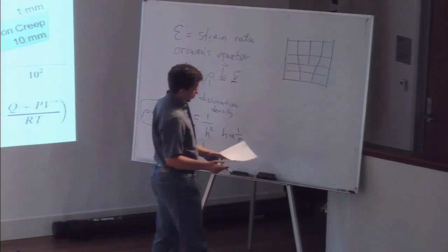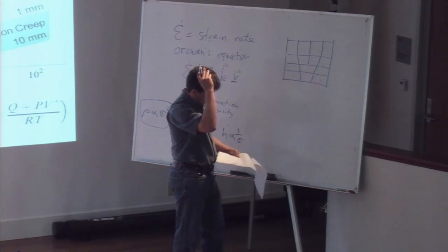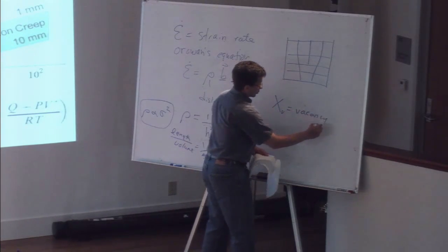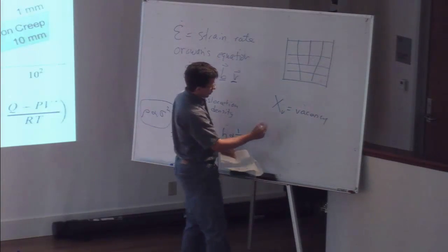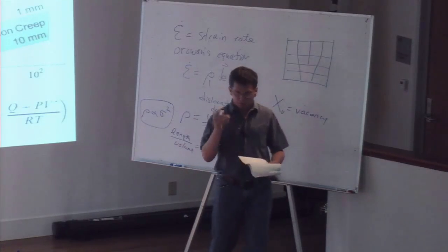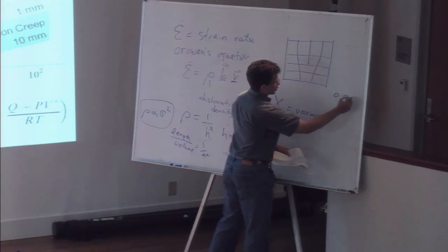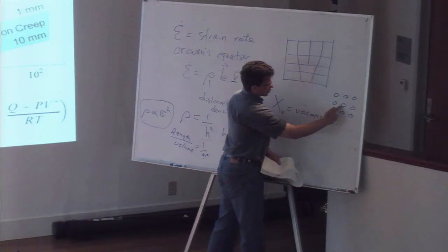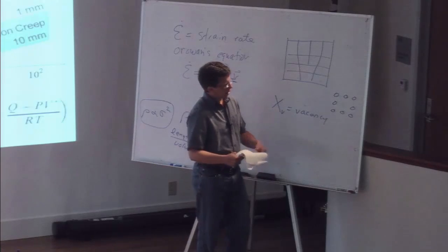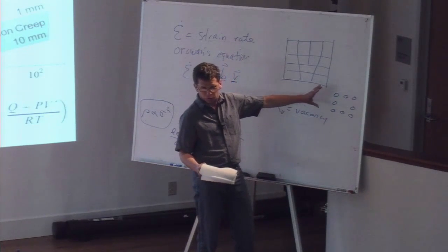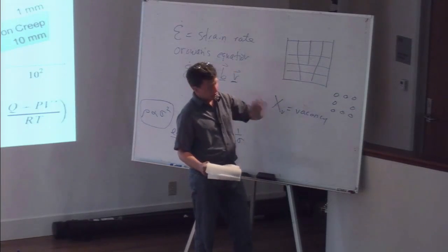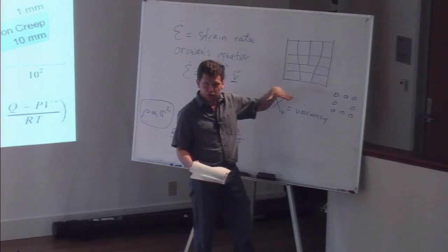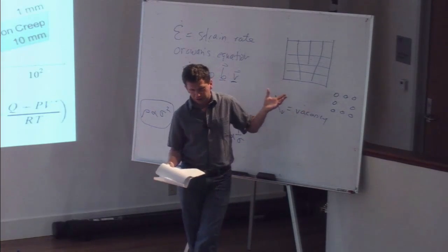Okay. So the vacancy concentration, which we'll denote with X_V, is related to pressure and temperature. To give you some concept of what we're dealing with, these are now atoms. If I want to create a vacancy, say I want to stick it in there, I have to break a bunch of bonds, and then I also have to distort the crystal structure, okay? And there's actually an equilibrium concentration of the vacancies that gets higher and higher at higher temperatures, and that's owing to the entropy of mixing, if you know about thermodynamics.